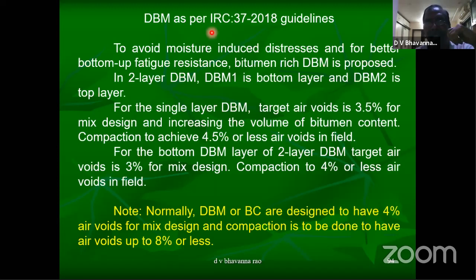Also, in IRC 37:2018, it gave some guidelines for the DBM because they wanted to avoid moisture-induced distresses and for better bottom-up fatigue resistance. Bitumen-rich DBM is proposed. Actually, we have to use more bitumen for the DBM bottom layer, that is, more bitumen than specified in the specifications. In two-layer DBM, DBM grading 1 is to be adopted for the bottom layer, and DBM grading 2 is to be adopted for the top layer.